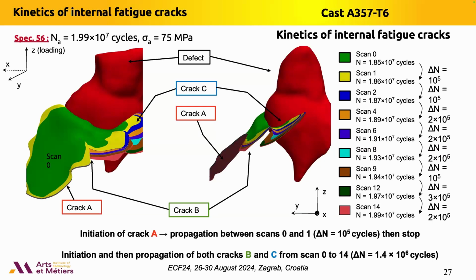So again, we have observed 3 cracks, but this is another specimen. I gave the same names, crack A, B, and C, but the crack configuration is completely different. Here, illustrated in false color, is the initial crack that was detected by our testing system. The first crack is in green here. It was detected after 1.85 10⁷ cycles. And then step by step, you have here the increments of number of cycles that were decided to observe the crack propagation step by step. So we have observed the crack initiation on crack A, and finally this crack was stopped, and we have then observed the propagation of two other cracks, B and C.